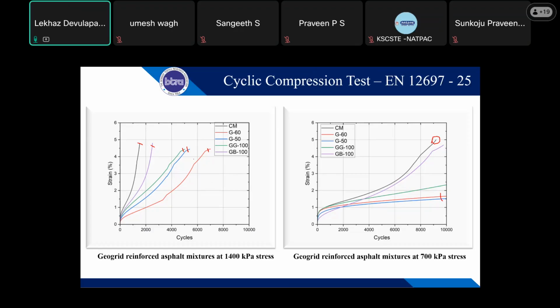So you can see at 700 kPa stress, even after 10,000 cycles, it was less than 2% strain.